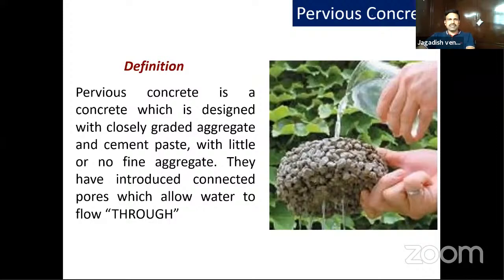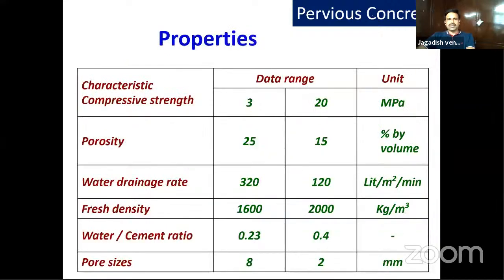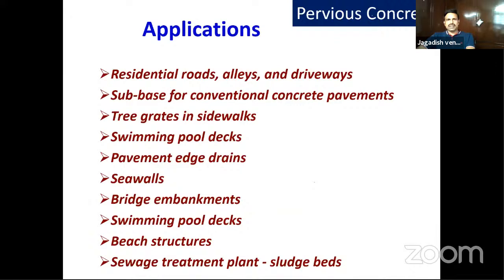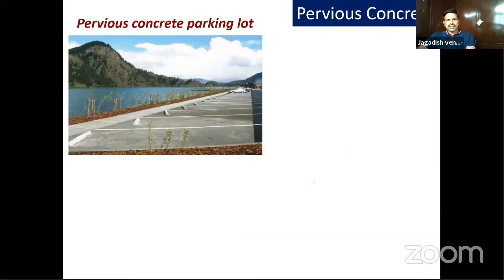Next is pervious concrete, which you can also call no fines concrete. You will allow the water. In other cases, we don't allow the water. Here you allow the water through the concrete. So you design the concrete based on the water drainage rate per minute in a 1 square meter area, how much amount of water you will allow. So the range is between 120 to 320 liters. The density is also between 1600 to 2000 kg. There are a lot of applications, particularly residential roads, driveways, swimming pool decks, and so on, wherein once the rain comes, it won't stagnate, it passes through the pervious concrete and joins the nearby drainage system.